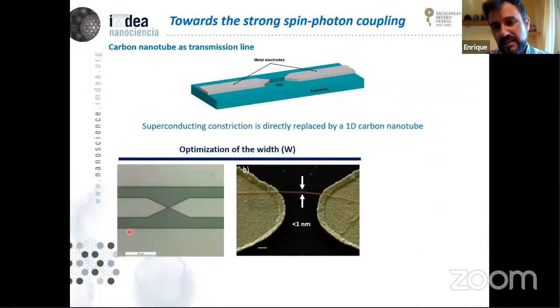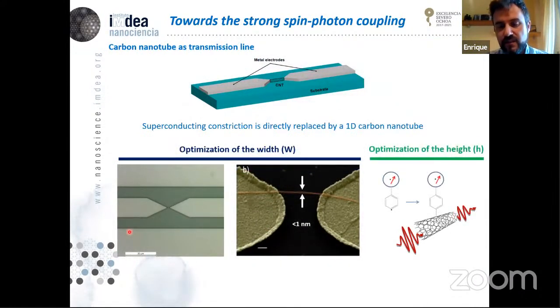But the carbon nanotube has an extra advantage, and this advantage is that it's very easy to functionalize with molecules, and in our case with magnetic molecules. So we would be optimizing not only the width, but also the height. It would be minimum, we should try to do it minimum. The additional advantage is that when we want to work with individual molecules, it's really complicated to place an individual molecule in a very specific place of a device. So with the carbon nanotube, we could use it as a vessel to really locate the molecule in specific places.